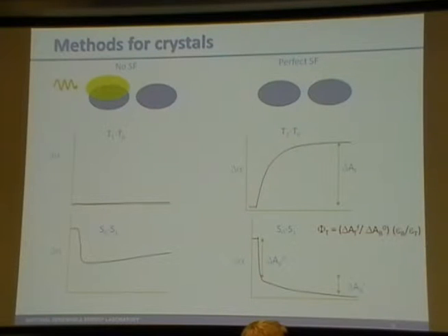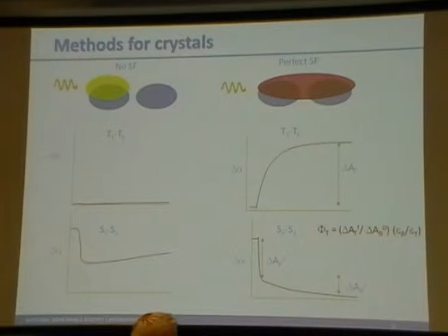So if you have singlet fission in the crystal, you excite with one photon, you initially form a singlet state, so you still have the same situation. Initially no triplet, and initially a large bleach component. Over time, if singlet fission happens, then you have these two excitations that live across at least two molecules. And so there's a change. So you see the kinetics, the rise of the triplet here, so let's say it's a picosecond or nanosecond time scale. And you also see the additional rise of the bleach component. And the reason you see additional rise of the bleach is that you've gone from essentially blocking one molecule from absorbing to blocking two molecules from absorbing. And so you see an initial rise in the bleach and a secondary rise.